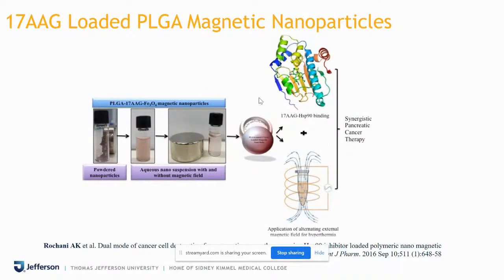The first formulation which we developed was 17AAG loaded PLGA magnetic nanoparticles. The design was very simple. You see a maroon color powder, and when you put it near the magnet, it just sticks to the magnet. The maroon color comes from the drug because it's a colored compound, and Fe3O4 is a slightly darkish black colored crystalline powder.